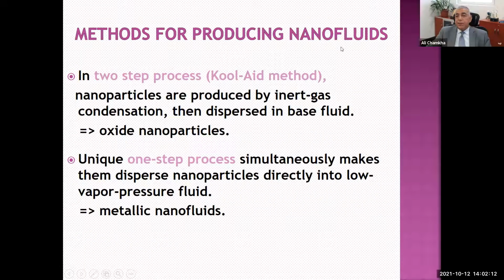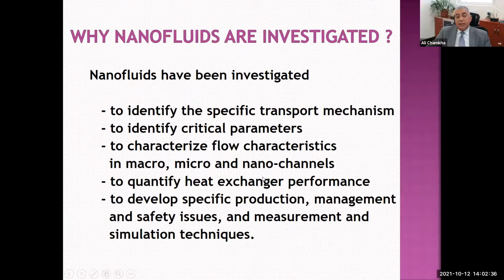Methods for producing nanofluids: we have the two-step process. Nanoparticles are produced by inert gas condensation, then dispersed in a base fluid. This is used usually for oxide nanoparticles. Then there is the unique one-step process, which is better. It simultaneously makes and disperses the nanoparticles directly into a low vapor pressure fluid, and this is usually used for metallic nanofluids.